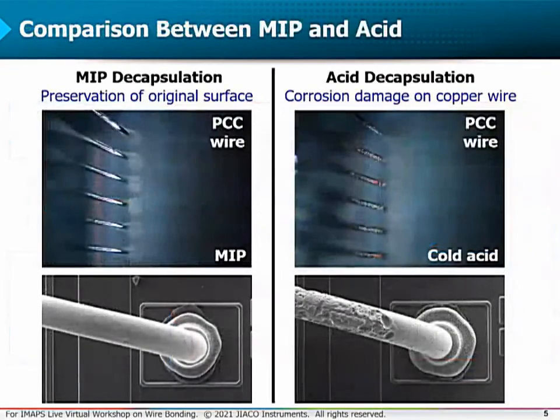Okay, this slide gives a comparison between results of MIP and acid. On the image on the right, we have a device which contains palladium-coated copper wire and has been decapsulated in cold acid. As you can see, the neck of the wire has been severely damaged by corrosion. On the image on the left, you can see the same device decapsulated by microwave-induced plasma, where we can see that the original surface has been preserved and no apparent damage on the bond pad, wire, and ball bonds has been observed.